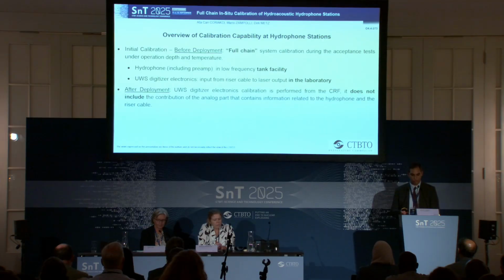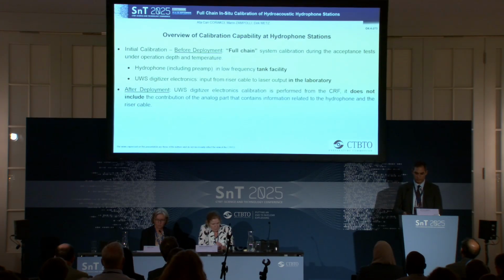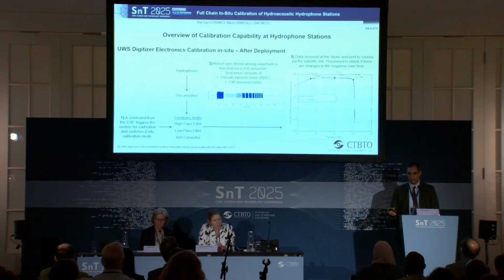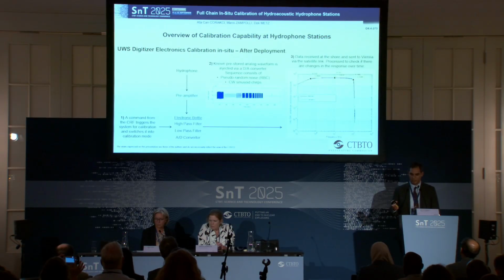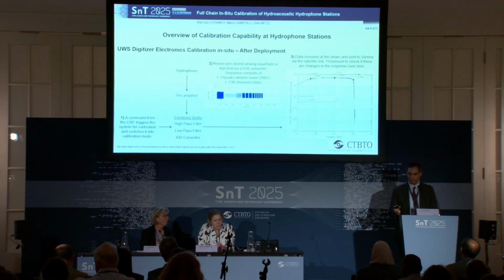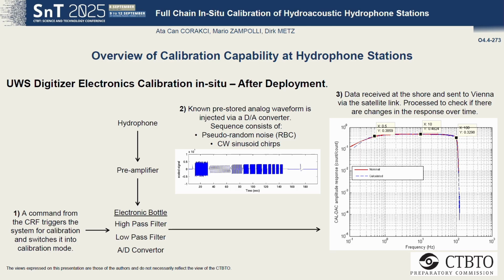So that means that the contribution of the analog part is not considered in the calibration. And this analog part contains the hydrophone, the riser cable, and the preamplifier, which is very critical from our perspective. And this is how the calibration is done after the deployment. From the CRF, a signal is sent to the electronic bottle, different types of signals, a continuous signal that we trigger from the CRF, and the electronic response is captured and compared with the nominal response of the system that was initially calibrated during the factory acceptance test. So you see in here, the hydrophone and the preamplifier are not considered in this chain.